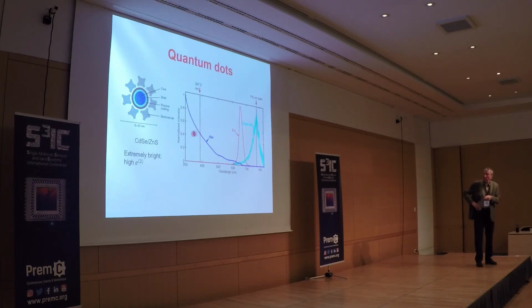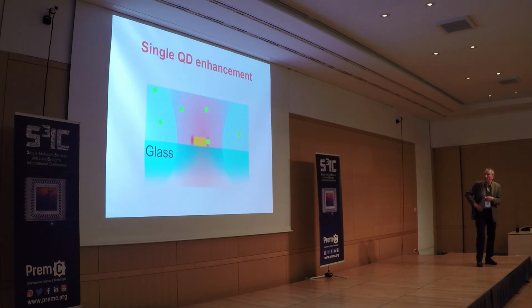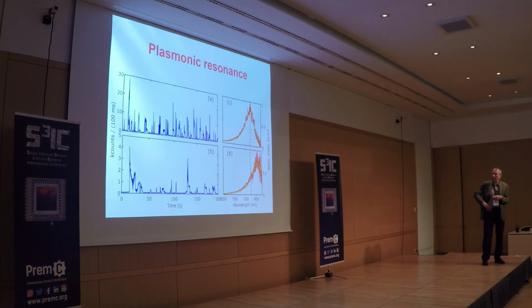So you see a quantum dot here, which is properly conjugated. And this quantum dot is going to stick transiently to the surface, and we're going to try and see this two-photon excitation. So this is the idea of the experiment. The quantum dots come here, they stick either to the rod or to the surface, and we try to see transient signals coming from this sticking. And this works with nanorods because they are so bright.